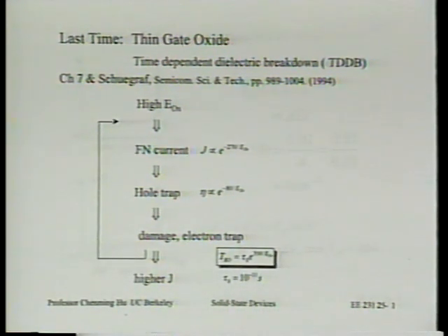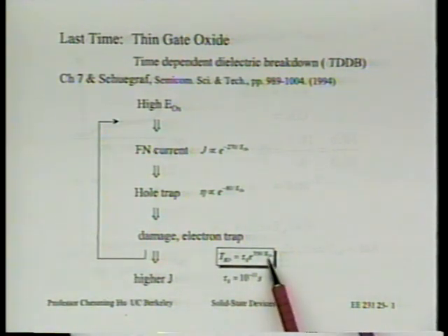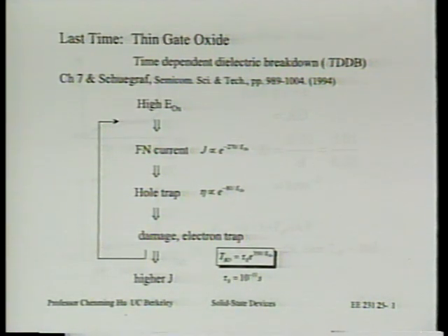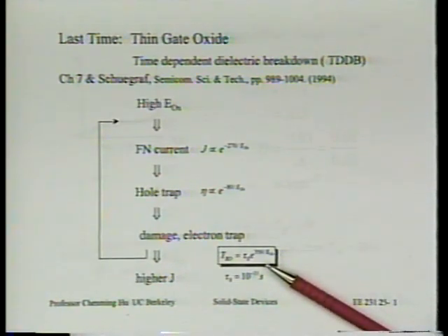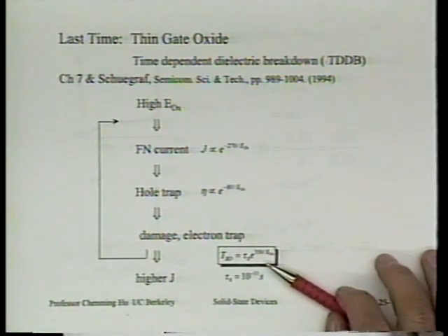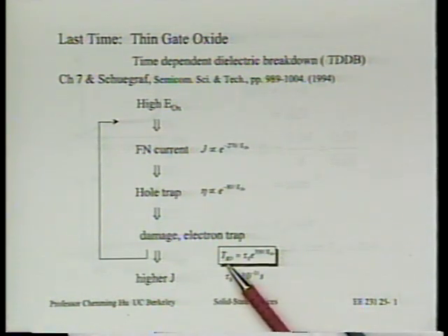From the equation, you can split the right-hand side into two parts. If you take the inverse of the failure equation, that's really a damage rate, and that rate will be larger for higher field. So during burn-in you are damaging at a fairly high rate, consuming a certain amount of the oxide's life. You should then be able to answer how long the remaining life will last at a given nominal VDD and nominal field.